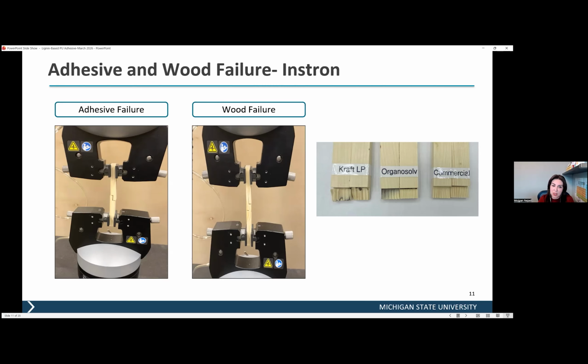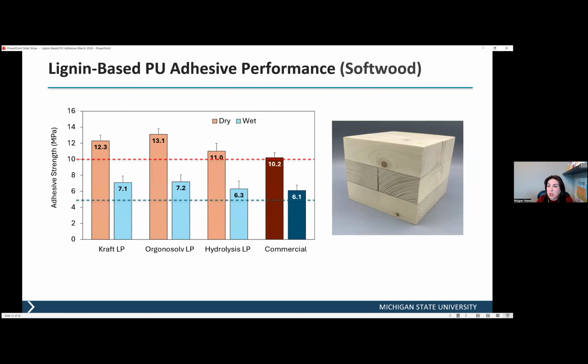Not only do we measure the adhesion strength, but we also look at percent wood failure, both in dry and wet tests. This is an example of the CLT samples that we made with the lignin-based adhesive. You can see that very thin black color, and that shows we used lignin-based adhesive.